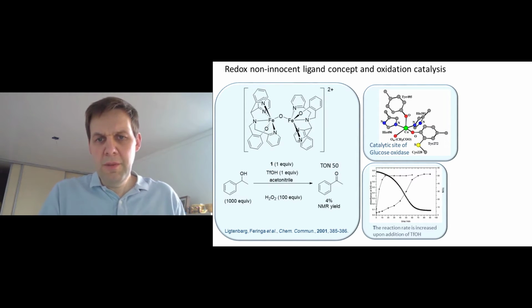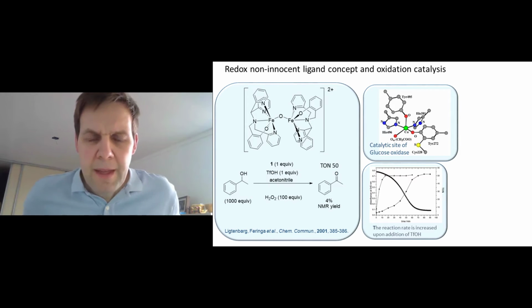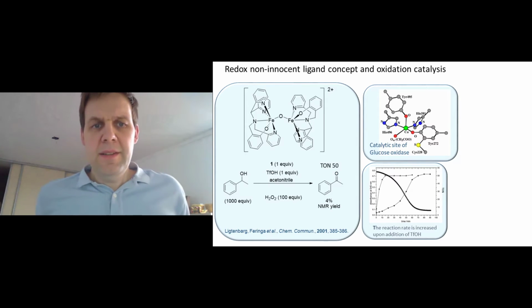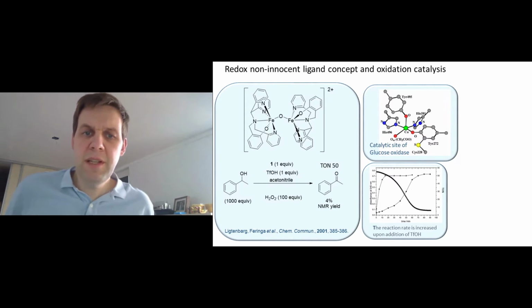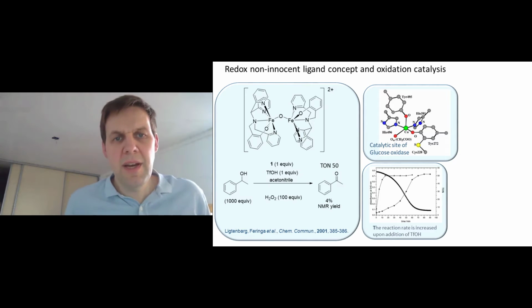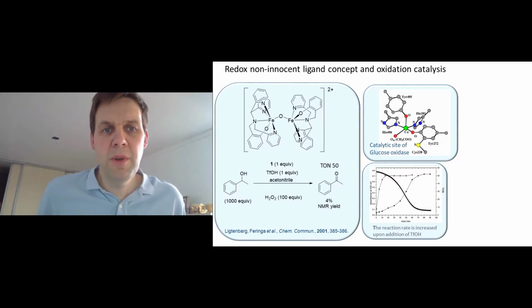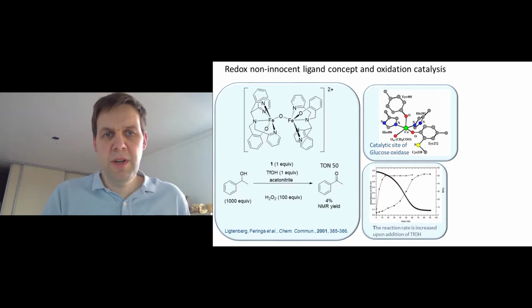Now, a remarkable effect is if you see with the triangles, such as this very short line, which you see at the start, if you add triflic acid to this catalyst and then do the reaction, it goes immediately and very quickly. So there's an idea that the addition of acid, for example, breaks up this mu-oxo bridge between the two iron centers, and that kick-starts the reactivity of mononuclear iron complexes. Okay, so